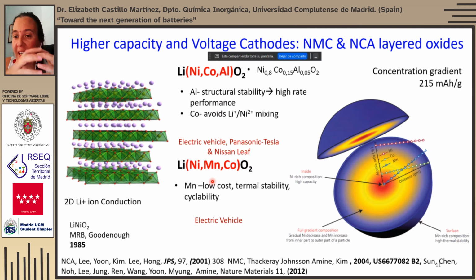of spherical secondary particles. So the material is synthesized having a gradient of composition, so a pure nickel phase, I mean doped with cobalt to avoid the anti-site disorder, is formed at the core of the particles, but there is a continuous gradient in composition as you go towards the outer surface, and the composition becomes manganese-rich to avoid reactivity with the electrolyte. And this gives a material with a capacity of about 215 milliamp hour per gram, which is quite high compared to the 140 of the lithium cobalt oxide.